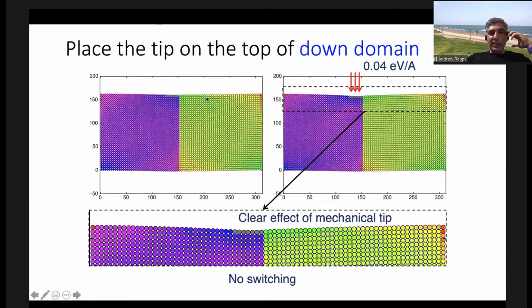Okay, so we start with the pretty much flat surface, but you can actually see that the up domain, which is green, is a little bit higher than the down domain, which is in purple. Okay, so we're going to start by pushing on the down domain. And you can see this is vacuum up here in white, and this is the top layer. And now that we've pushed, the atoms are actually shrinking down because we're pushing on them. And the system, when it's totally under no pressure, starts way up here. And this is how far it's compressed already just by pushing with the tip, but no switching has happened yet. This is gentle pressure. And so we have to up it a little bit. We start to push harder.